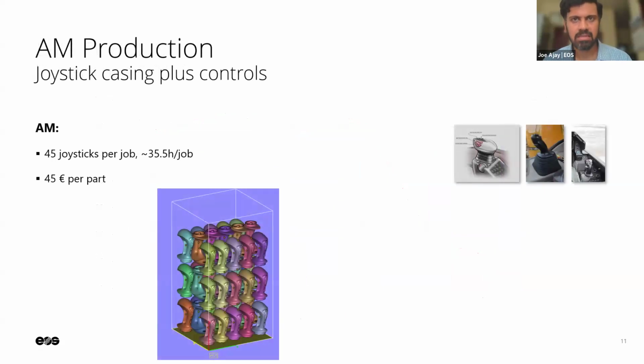So this is a production case similar to what you saw on the engine casing. Let's say this is a product, a joystick. We use it for gaming consoles or off-road vehicles, and so on. So this part, if it has to be printed in a small series, such as 36 parts or a little lower than that or a little higher than that, about 50 parts or so, we can print 45 of such parts in one full job, and that takes roughly about 2 days of time. That quick is what our process is.